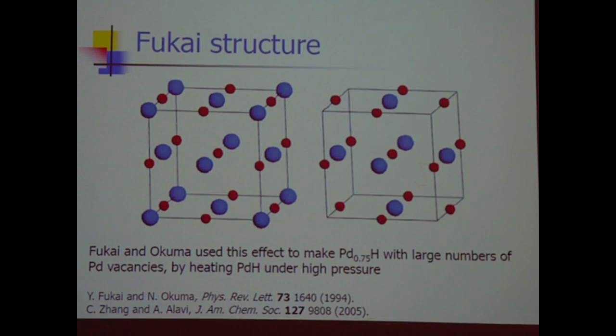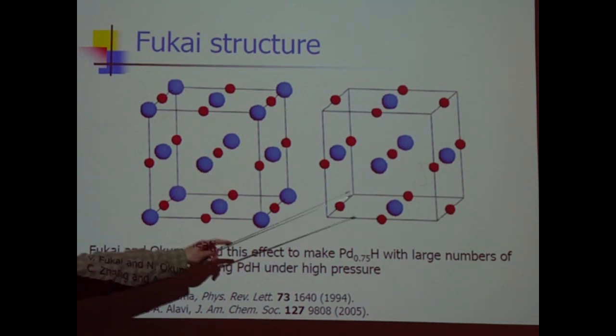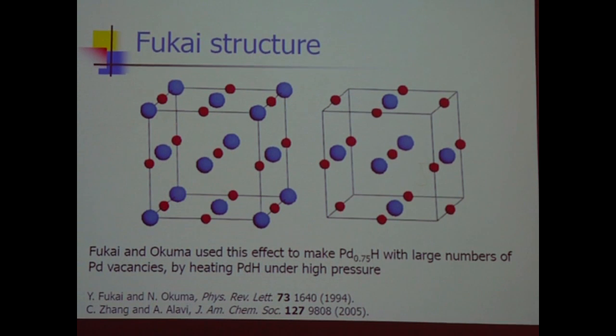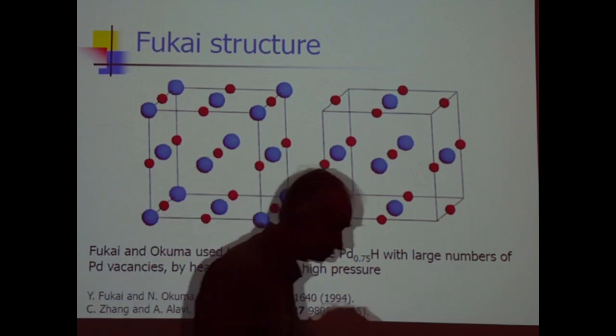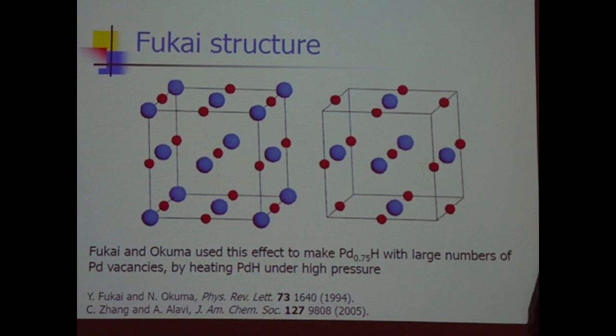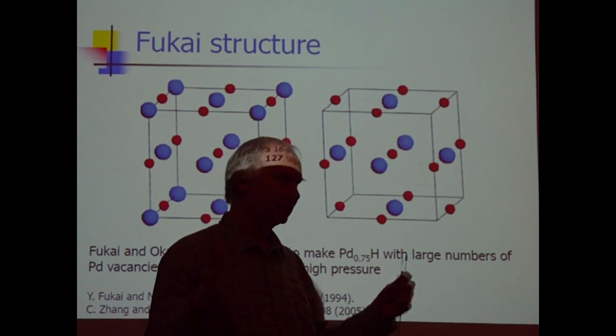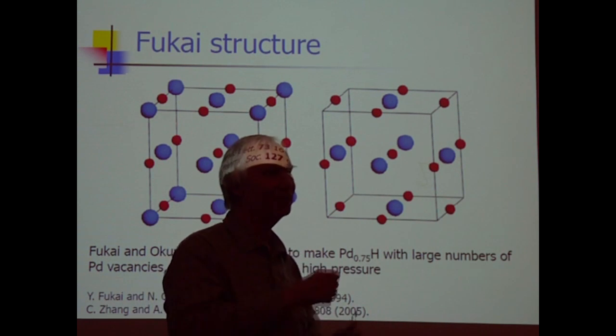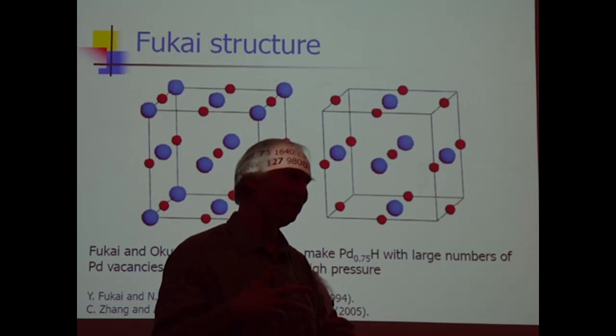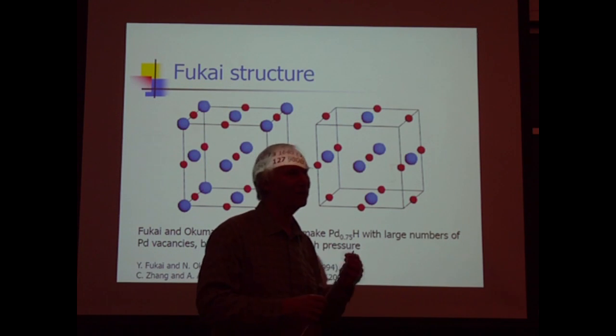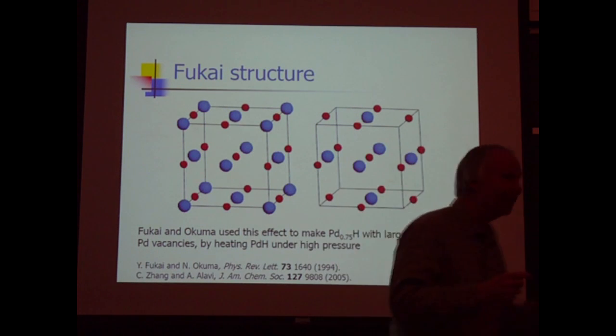If you want to make molecular D2 in palladium deuteride, you don't want to work with this, because the electron density is too high everywhere for D2 to form. But if you got this, then you have electron density low enough that you can have D2 formation. If you have so many vacancies, would you notice that on the volume of your lattice? The volume shrinks a little bit. If you like, we notice that addition of hydrogen stretched out the lattice, made the volume bigger. Well, you take hydrogen, you take palladium out, and the lattice shrinks a little bit. It's a smaller lattice constant.